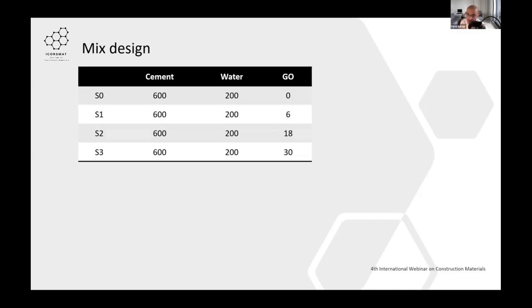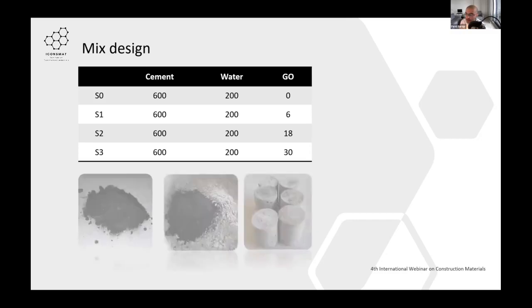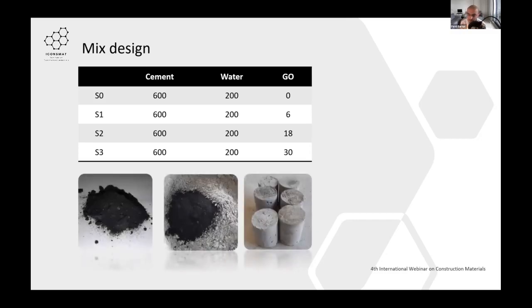Cement and graphene nanoparticles had been mixed first, and water was added slowly in the mixer. The mortar had been mixed for 5 minutes, and 4 different samples were obtained at the end, as you can see right here. To get rid of the air bubbles once poured in the mold, the samples had been vibrated for 1 minute and left in a water tank for curing after 24 hours for a duration of 3 days.